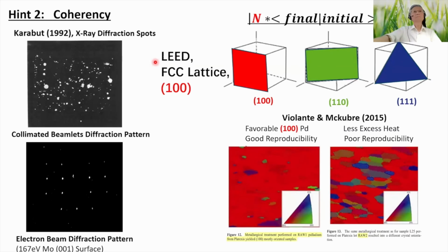From low-energy electron diffraction theory, we may see that the face-centered cubic lattice is best to increase N. This lattice has three kinds of surface, and the 100 surface is best to increase this number. Dr. Violante and Dr. McKubre showed two palladium samples with the same metallurgical treatment. This one is 100 surface dominant. It has good reproducibility with large excess heat. This one is a mixture of surface orientations. It has poor reproducibility with less excess heat. So 100 is good for a big N number.